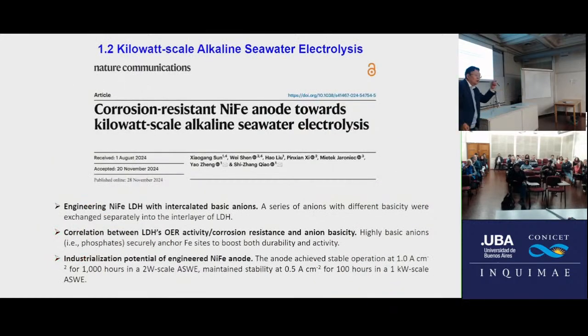Okay, so I just introduced a PEM system for direct water splitting. So here we use the alkaline seawater electrolyzer system. Okay, so normally for pure water we use nickel catalyst. However, nickel cannot operate in seawater, it loses activity rapidly. Okay, here we use nickel iron catalyst. Even that is unstable, so we must modify it with different ions. Okay, so we establish a relationship between the OER activity and the corrosion resistance of this material with the ion basicity.